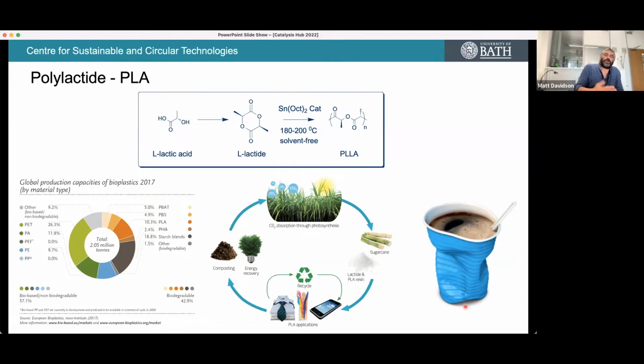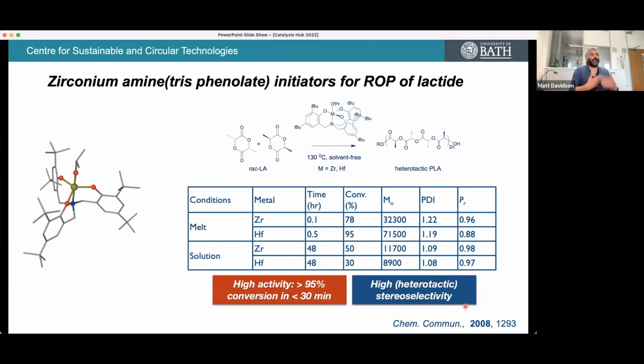But there's a significant interest in enhancing the physical and mechanical properties of PLA, and many people around the world, both industrial and academic groups, have been working on that for a number of years, and there's many ways you can do that. A number of years ago now, and again, this is just by background, and I don't want to go into this in any detail, we discovered a class of catalysts, amine trisphenolates, particularly these zirconium ones with a crystal structure of 1 over here, they're C3 symmetric alkoxide terminated amine trisphenolates. It turns out that they're highly active and highly stereoselective catalysts for the ring opening polymerization of lactide.